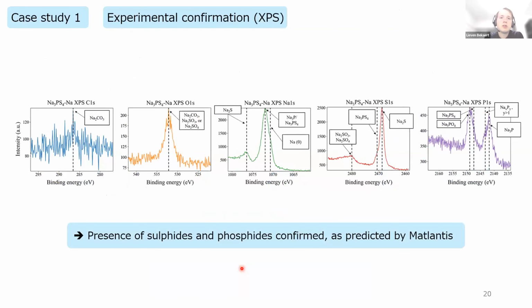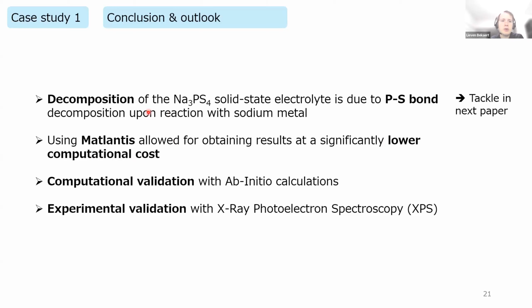And we went one step further, and we also performed experiments. We analyzed the decomposition products at the sodium and Na3PS4 interface with XPS. And we confirmed the presence of sulfides and phosphides, which is in agreement with the results from Matlantis. So we confirmed this also experimentally. To summarize the first case study, we found that the decomposition of this Na3PS4 solid state electrolyte is due to PS bond decomposition upon reaction with sodium metal. And as I will show you in the next case study, this provided a starting point for improving the stability against the sodium metal electrode. We also found that using Matlantis allowed for obtaining results at a significantly lower computational cost, and we were able to validate this computationally with ab initio calculations and experiments.